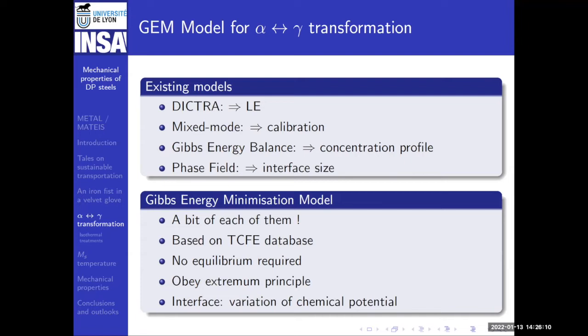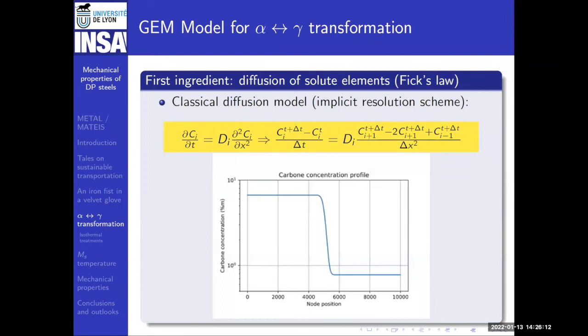So to build this model, we start with the first model, which is extremely well known and nothing new. We just model the fact that a diffusing element, a solute atom gradient, will naturally transform into a flat profile. So first ingredient, diffusion. Diffusion of, for example, carbon or manganese or any kind of solute elements in the steel, in both ferrite and austenite. First ingredient, diffusion.